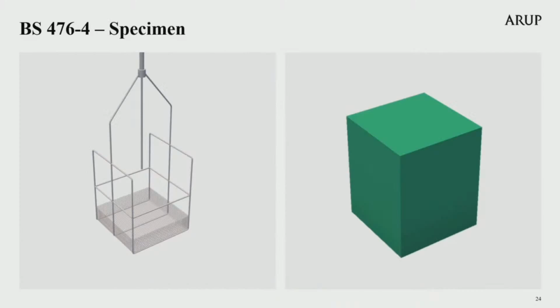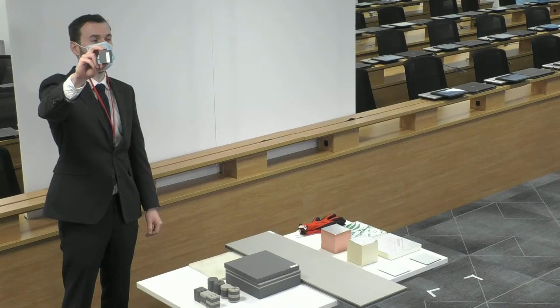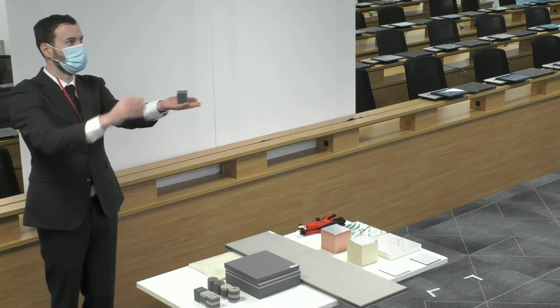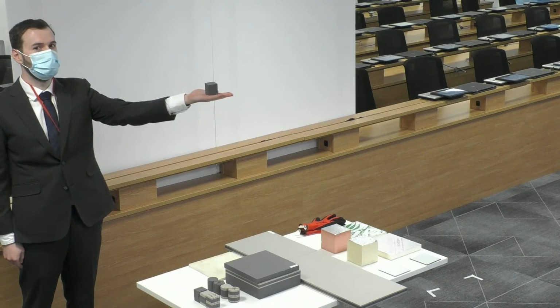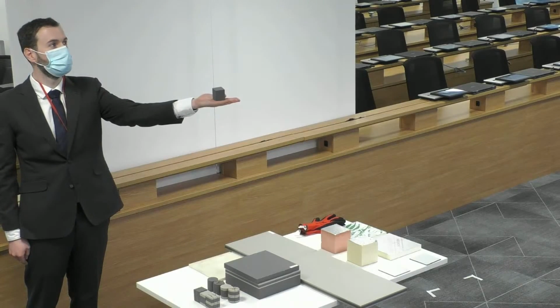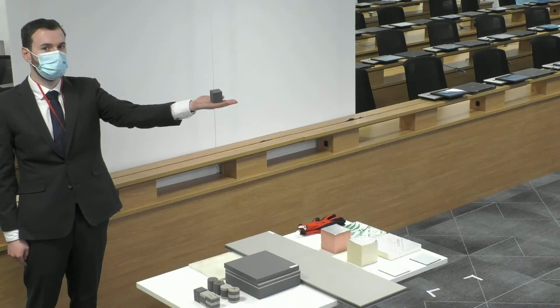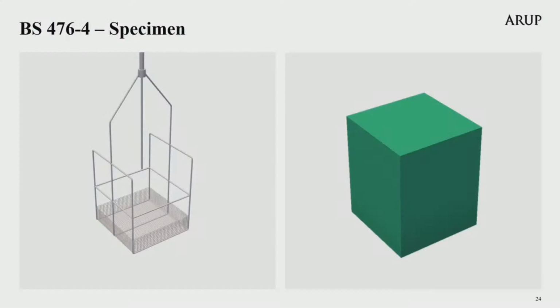3 specimens are prepared, each side a length of 40 millimetres with a height of 50 millimetres. My colleague Tom is now holding up an exact replica of the size of the Part 4 specimen. One complete test consists of testing 3 specimens, each specimen tested separately in the furnace. The specimen is placed in the specimen holder, which is shown in the image on the left. This holder is 100 millimetres high.